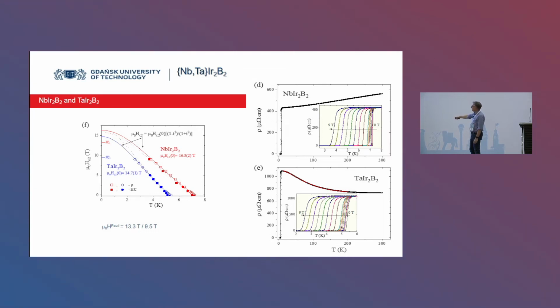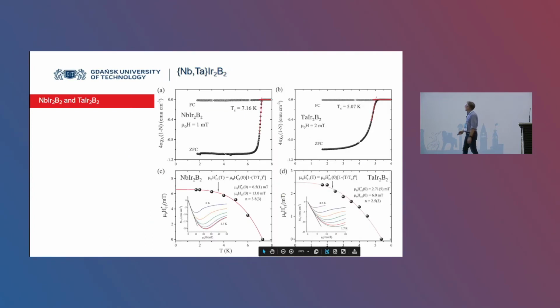For the tantalum compound, it is 14 Tesla. Here is almost 9 Tesla. So it's above the Pauli limit. Magnetic susceptibility shows the Meissner fraction. The transition here is very sharp. For the tantalum sample, it's not so sharp. Now we have better samples.